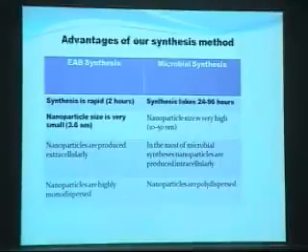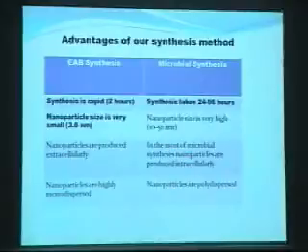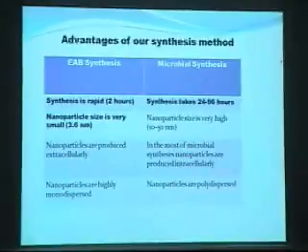And this is very important: nanoparticles are produced extracellularly. Meanwhile, most microbial synthesis produces nanoparticles intracellularly, so it is very difficult to separate them from the biomatrix. Here we can separate easily, because of the extracellular production. Then monodispersity: normally the biological method gives highly polydispersed nanoparticles, but in our case we get more or less monodisperse nanoparticles, which is very important for practical application. If you want to apply them in some electronic device, we want monodispersed nanoparticles instead of polydispersed. So totally, the proposed method gives a high advantage over previous reports.